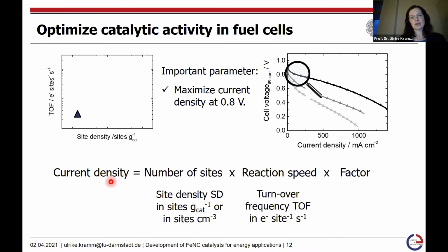That means when we would like to optimize our catalyst, we typically would like to go in this direction in order to maximize both the site density and the turnover frequency. But very often we either go for higher site density or higher turnover frequency. So now we need to understand how we can determine the site density in this type of catalyst material. And that's indeed not as easy. We have a black catalyst powder, and in contrast to platinum, we do not have nanoparticles, but we have molecular centers which are integrated in the graphene sheets.